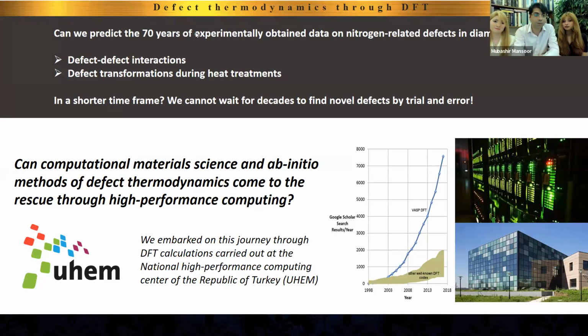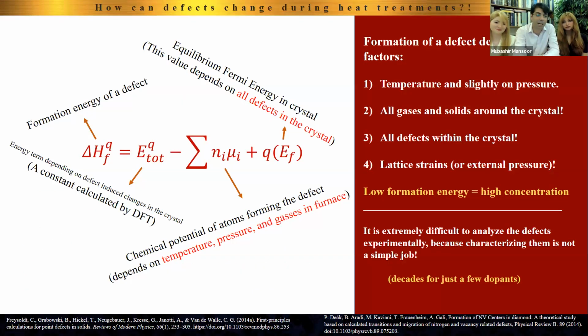Exactly. We considered if we could perhaps predict the 70 years of experimental data that is on diamonds, and we could actually calculate them on the nitrogen-related defects. We started this with diamond because diamond has a great deal of published literature. But if we can do this in diamond, it means we can also do it in sapphire. We can also do this in all sorts of other material. Exactly. So we are fortunate enough to have this UHEM supercomputer at ITU, where we actually applied these calculations.